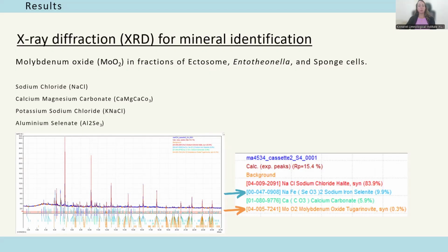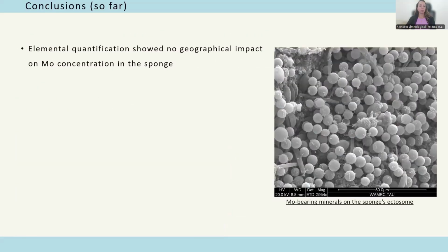Importantly, calcium molybdate was not confirmed by XRD, and there are several possible explanations. The calcium and molybdenum-rich granules may be amorphous, poorly crystalline, present below the detection limit, or masked by the dominant salts such as NaCl. For me, the important message here is that molybdenum is present in mineral-associated forms, but the exact mineral identity is not fully resolved.